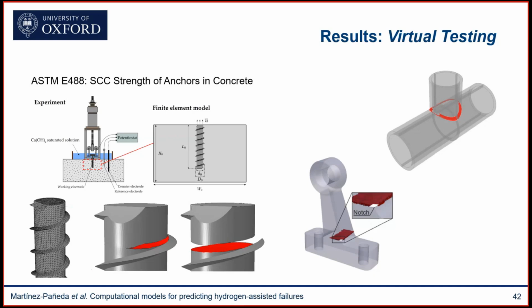And we can simulate anything. We can simulate many other standardized tests, no matter how complex they are. So we know there's a lot of hydrogen embrittlement problems in anchors, bolts and screws. So you can simulate this kind of classic ASTM standard test where you have a metallic screw in concrete, and you have the screw subjected to an aggressive, hydrogen-containing environment.